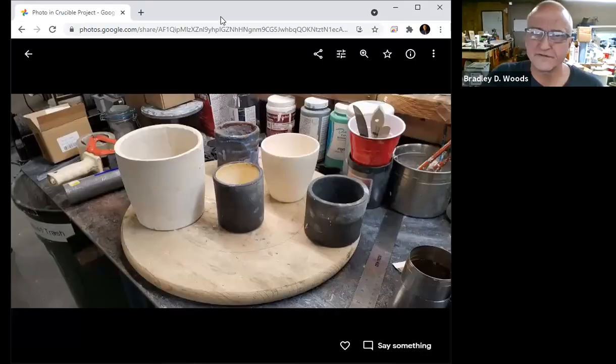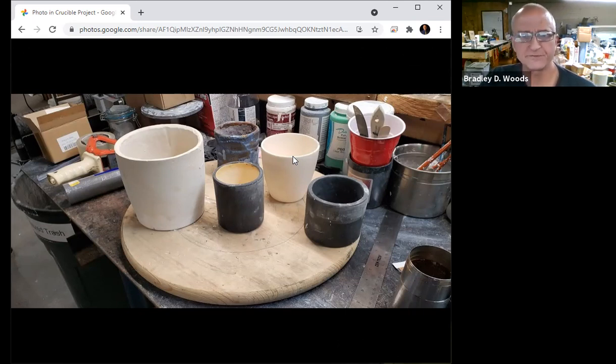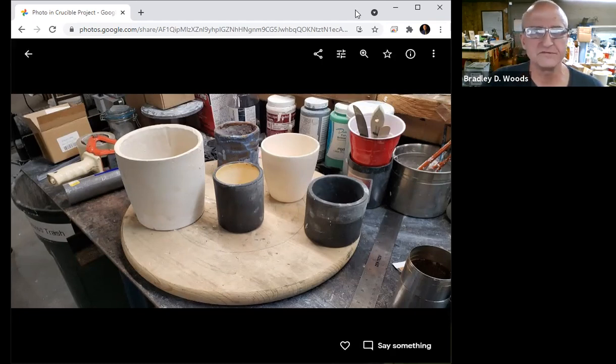So exactly the same parameters, the black ones get substantially warmer more quickly than the white ones do. And the effect is much more substantial than I thought was even possible. So in our sintering cycles, we're dealing with variations in temperatures as low as, say, 15 degrees Celsius that will have an impact on the final product. So these are just meant to be more consistent.